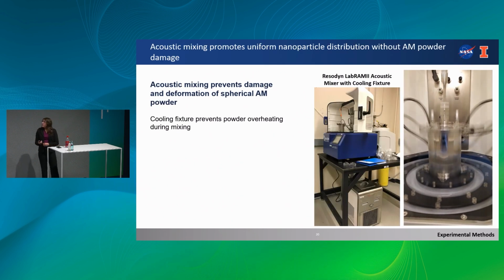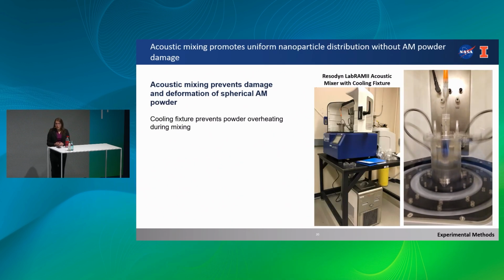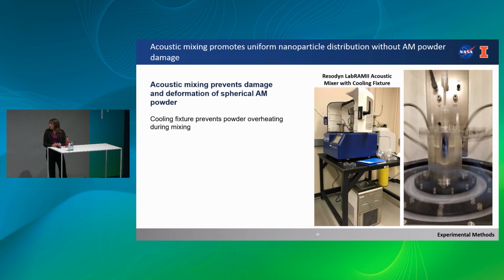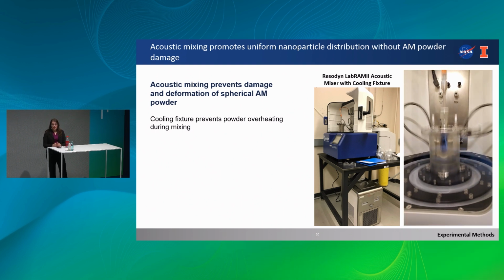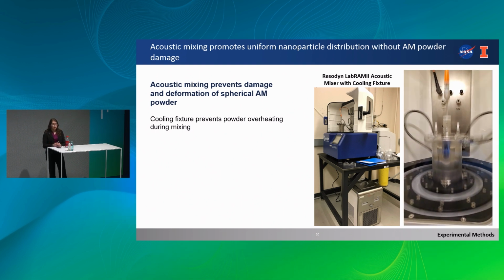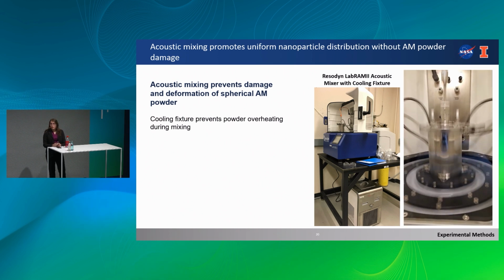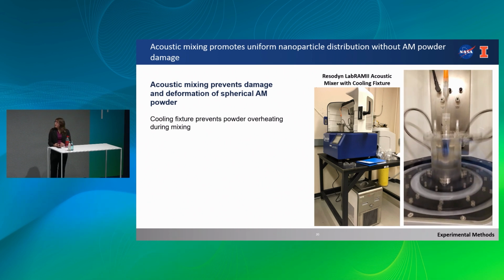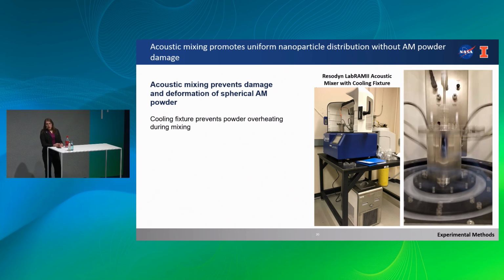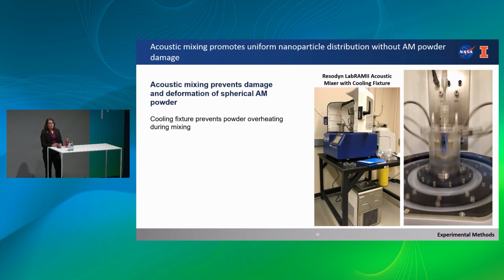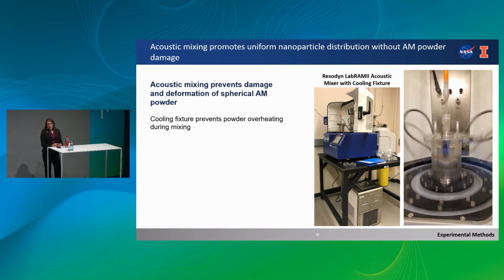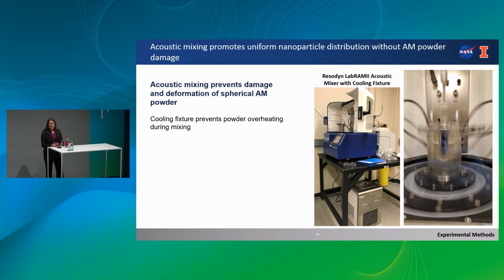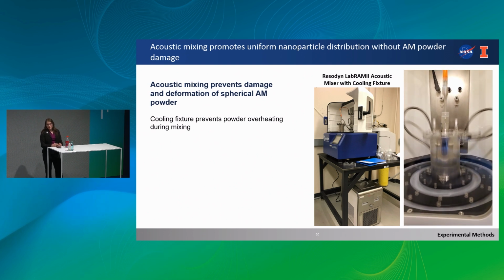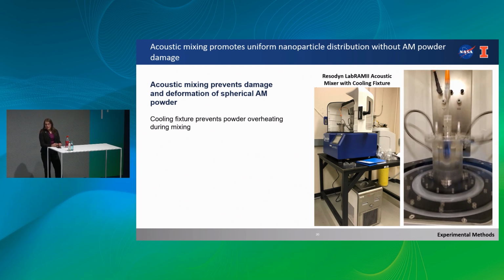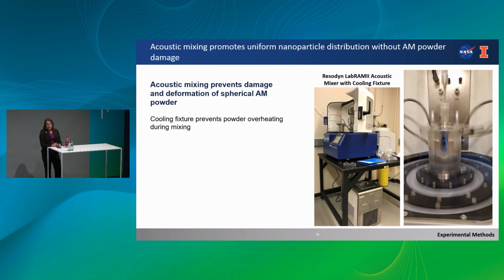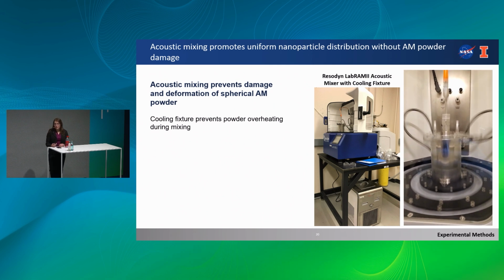To mix the nanoparticles in with our metal powder, we used an acoustic mixer, and this is a really great process. We also have a cooling fixture. This is just to help prevent overheating of the powder, and basically it keeps it nice and cool throughout the mixing process. The nice part about this approach is that we can mix a decent amount of powder pretty quickly, and not have any issues really with the results. We don't have any damage to the powder or anything like that.